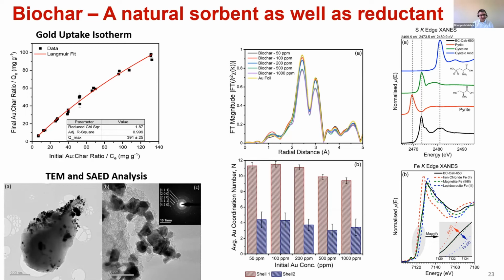Then we were able to use TEM and diffraction analysis to show that indeed gold clusters were formed on the biochar. The way we tried to rationalize this is we did sulfur and iron XANES on these materials, and we found that most of the sulfur budget is in the form of reduced sulfur groups like cysteine and methionine, which are known to reduce things. But more importantly, it had mixed iron 2 iron 3 oxides, more like magnetite, which is a very potent reductant, of course, and that reduced gold. Gold can be reduced relatively easily. That's a known thing. We further conducted XAFS analyses to show that there was a difference in the first and second shell, and that the size of these particles was constantly getting smaller.